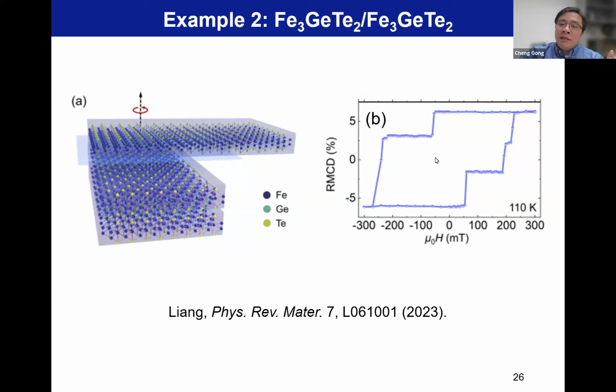But this smaller one and larger one differ from any of the original FGT. If you look at FGT coercivity here and here, you find these two differ from the two coercivity in the heterostructure region. So that means these two layers interact with each other and cause a change in coercivity, but they are not merging into one thicker FGT, which should show only one coercivity. So again, this is to highlight how the interfacial interaction is critical for the magnetic property.